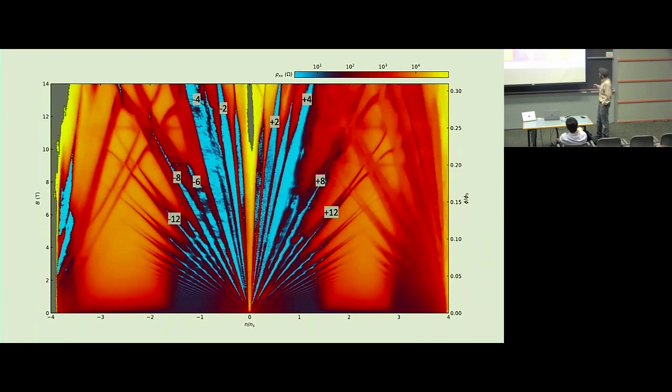And what you see is that splitting that I mentioned: half of the Landau levels terminate when they hit the magnetoresistance region in the fan, and half of them split into two when they reach this region, and then they cross the split Landau levels coming from fully empty or fully full.